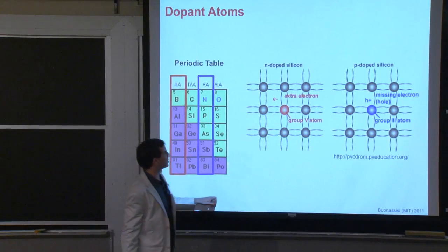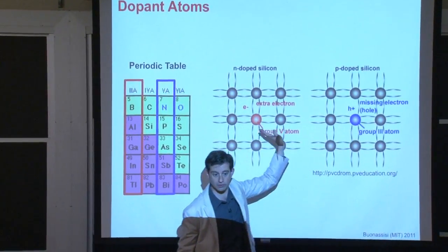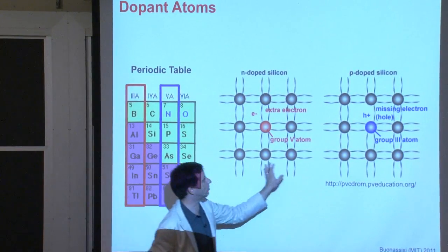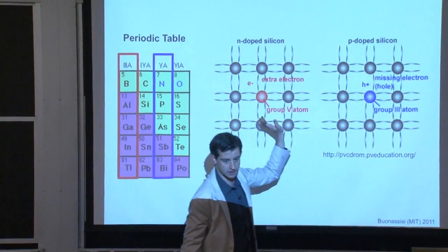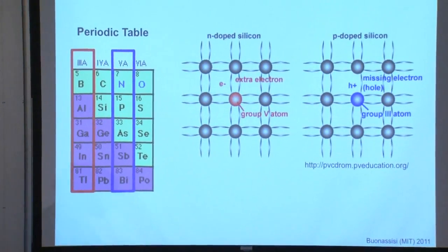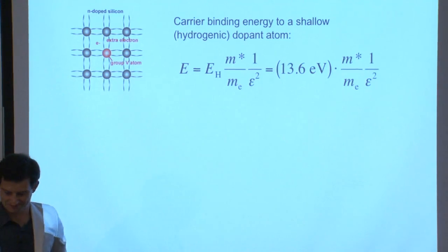Yeah, so it's an excellent question. The question, if I may paraphrase, relates to the hole and electron mobilities. How easy is it for them to move around the lattice? And typically, the hole mobility is about a third of the electron mobility in silicon. So absolutely, it is a little bit more difficult for those holes to move around. Holes, as you may recall, are quasi-particles.